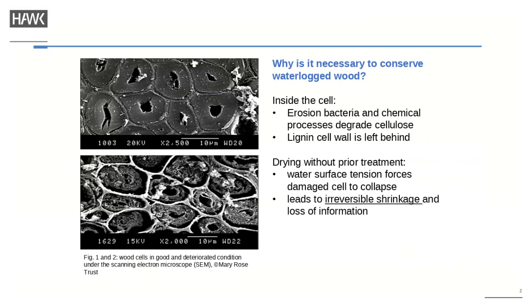Therefore, I have these two photos taken at the Mary Rose Trust, both under the scanning electron microscope. You can see on top a picture of well-preserved wood cells and underneath degraded wood cells. So what happened here is that due to erosion, bacteria or chemical processes, mainly the cellulose parts of the cell are being degraded, and what's left behind is the lignin parts of the cell, so mainly the cell walls, the whiter layer you can see here.